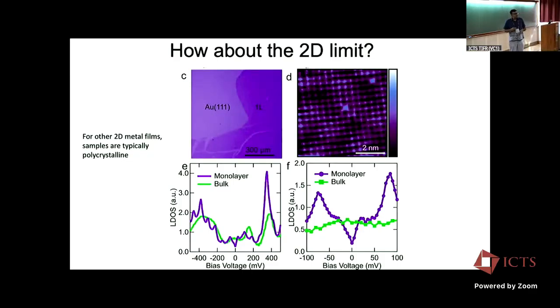So this is an exfoliatable metal. And so this is a perfect material where we can really look at localization physics by simply taking the material and peeling it and taking it down to 1 layer in thickness, right? And this is quite different from all the previous studies of 2D metal films. Of course, there are many beautiful experiments on semiconductors where you really have single crystal semiconductors. We heard a lot of that earlier in this conference.